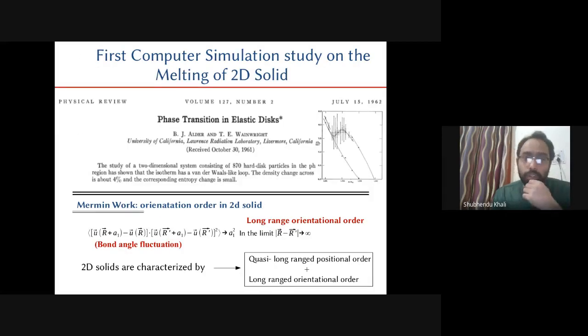However, in 1962, Alder and Wainwright showed their work on elastic disks, and they observed in their study that the system was showing phase transition kind of behavior. It triggered the scientific community's attention, and people started to understand how melting is happening in two-dimensional space. So in 1967, Mermin worked on two-dimensional solids, and he showed that the bond angle fluctuation in those systems remains finite, irrespective of the system size. So we conclude that 2D solids are characterized by quasi-long-range positional order together with long-range orientational order.